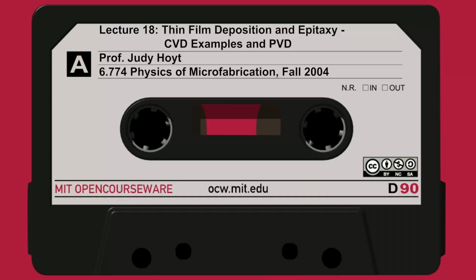Looking at slide 22, the sputter yield Y is a function of the energy. So that'll be dependent on the bias in the plasma, right, the voltage drop. And it'll also be dependent on the mass of the ion. Argon is very commonly used. It's very massive. And it depends on the target material. It'll also be a function of the incident angle of the argon coming in. The sputter yield doesn't vary that much, not nearly as much as the vapor pressure. Vapor pressure varies by 5 or 10 orders of magnitude among the elements. That's not the case with sputter yield. So sputtering is pretty good for depositing alloys.